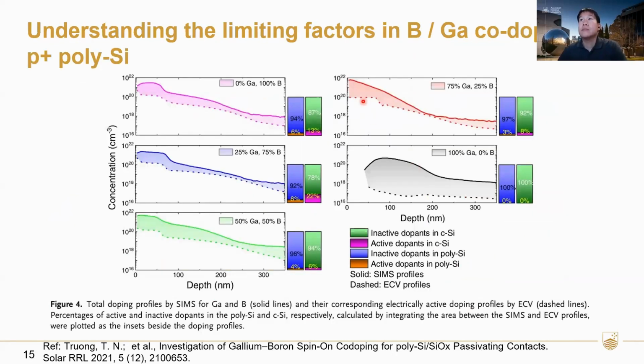We've also used SIMS for a quite commonly used comparison of SIMS and ECV measurements to look at active and inactive dopants. In this case, we've used it to understand the limiting factors in boron gallium co-doping of P+ polysilicon. This is work from my colleague Tian. In this case, we'll focus on this.